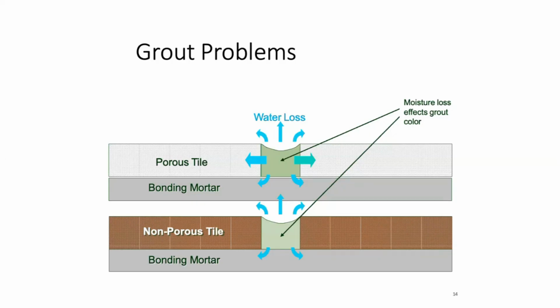Now you notice at the bottom, you'll see the non-porous tile. So as the porcelain tiles started coming into the market, they're not absorptive on the sides. So the moisture couldn't release left or right. It could only go down into the thin set bed and up. So now you're reducing that absorption rate, and that water was being trapped in that grout joint for longer than it needed to be. What happens with Portland cement is that the longer the moisture stays in the grout joint, the Portland cement creates what's called Portlandite, which is salts or minerals, and they end up floating to the top of the grout joint, and that's called efflorescence.